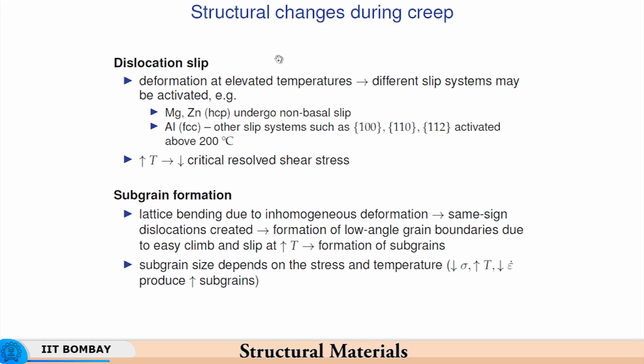Now, we need to therefore see the structural changes that take place during creep. So, one structural change would be that the dislocation slip or slip planes would change. So, the planes of easy slip will undergo a change. So, you can have a non-basal slip in case of magnesium and zinc, typically HCP structures, and in FCC structures you can have slip in these planes which will be activated above 200 degrees centigrade.